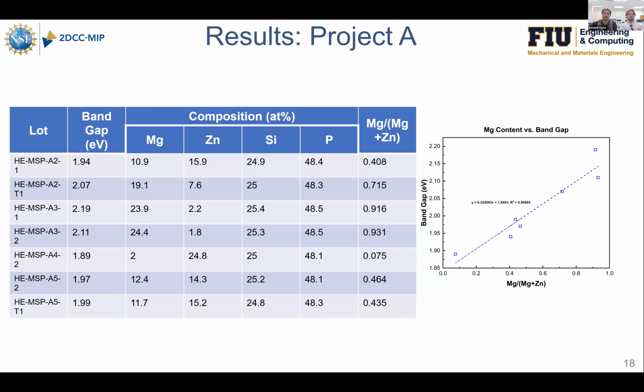However, with the crystals that we were able to image and get UV-vis spectra data from, we were able to identify a trend between the magnesium with respect to the total magnesium and zinc content. With the ones that were imaged, we found that with an increasing amount of magnesium, there is an increase in the band gap. This is validated by an R value of about 0.9, so the trend is pretty strong.